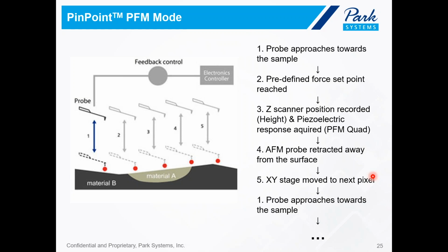Imagine for conventional PFM, since we are doing the experiment in contact mode, essentially if your sample is very rough, the tip can be scratching on your surface furiously, which will lead to tip wear, of course, and then degradation of your resolution. However, in our PinPoint PFM, the user can define the contact time depending on their sample. They can tailor all the conditions depending on the sample. So instead of constantly scratching on the sample, the tip and sample contact time is minimized, which will maximize the tip life.